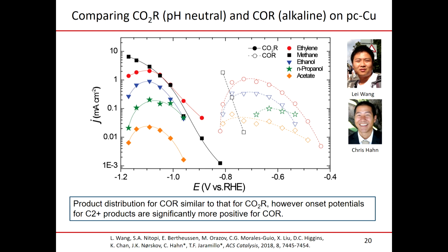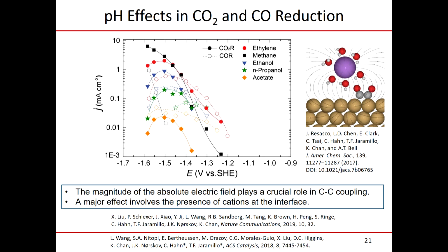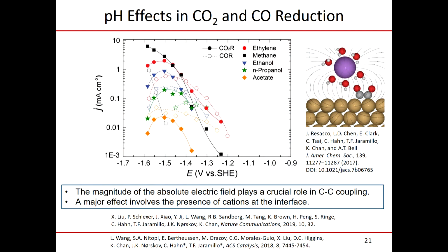You make your ethylene, your methane, your ethanol, propanol, et cetera. But you make a lot of these products half a volt earlier on the RHE scale, on a reversible hydrogen electrode scale. So that's half a volt of improved energy efficiency for your device. It's half a volt better for the C2 products, but only a quarter of a volt better for the C1 product of methane. And that's an interesting point. Why is this? It turns out that we think the CC coupling step is facilitated greatly by this electric field. And Mark had also mentioned this, when you have cations that are near that interface, it can really help stabilize these intermediates.